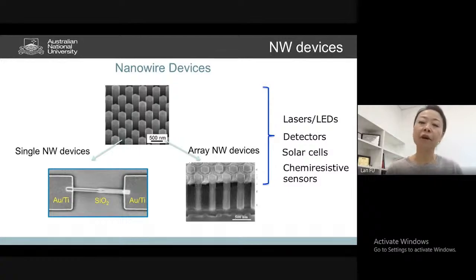Because they're so tiny, they are mechanically very fragile. So it's very easy to knock them down and transfer them to another substrate. If you use a piece of paper, or cut it with a sharp tip, and gently touch those nanowire arrays, you can transfer them onto a substrate to make a single nanowire device. So we're actually doing that. This is one example of a single nanowire device we're fabricating in our lab, a single nanowire LED, I believe. What we do is transfer it to the substrate and make gold contacts on the ends through nanolithography, and then we do measurements.